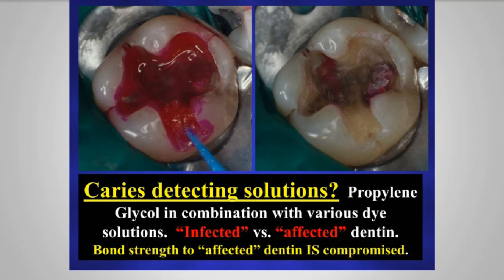So now I know it's commonly taught that it's okay to leave in affected dentin, and we can go ahead and do that. But one thing you do need to be aware of if you're going to do that, when you go ahead and put a dentin bonding agent on top of that affected dentin, you always get a compromised bond strength. There's many, many studies to show that. So yes, you can leave in affected dentin, but you can't bond as well to it. I personally like to make sure I really have a good, clean, fresh dentin surface before an adhesive procedure.